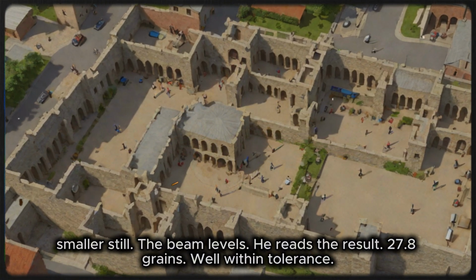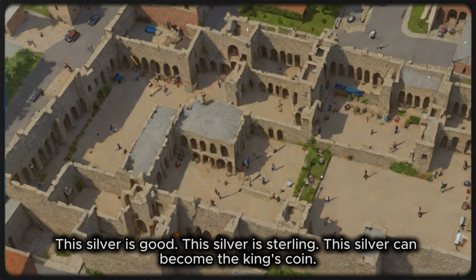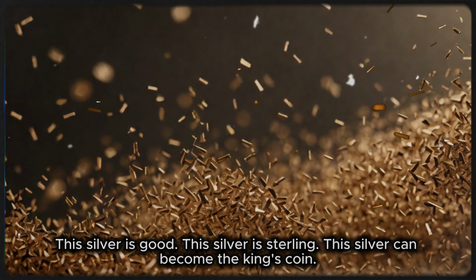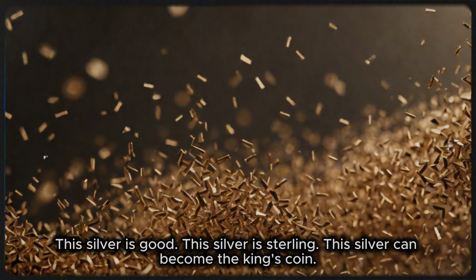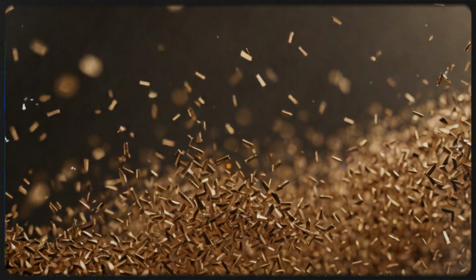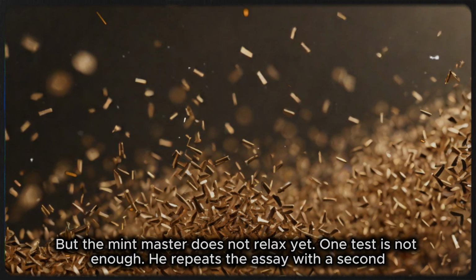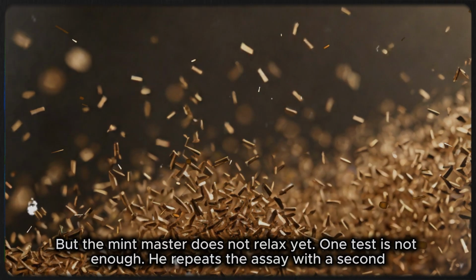27.8 grains. Well within tolerance. This silver is good. This silver is sterling. This silver can become the king's coin. But the mint master does not relax yet. One test is not enough.